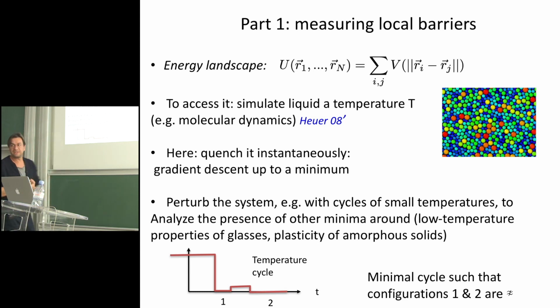And the way we're going to do it, because at the end we want to detect excitations, I will call them, that have a small barrier, we're going to use temperature. So you equilibrate the system, it's really equilibrated, you quench it, and then you do a very small temperature cycle, and if it's too small, nothing happens. You go back, configuration 1 at zero temperature here and here are the same, you didn't jump over a barrier. But we look at the minimal cycle where, yes, something happened.